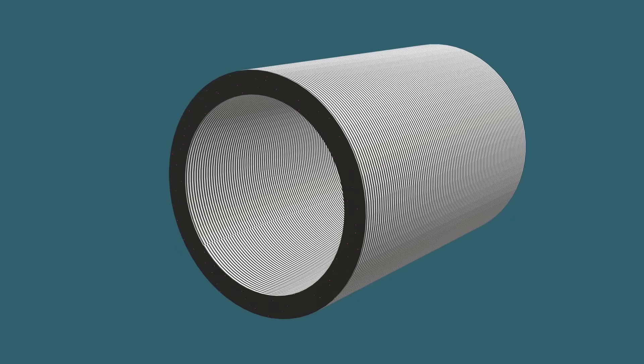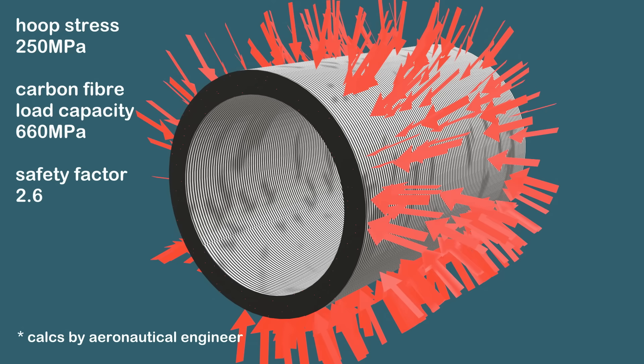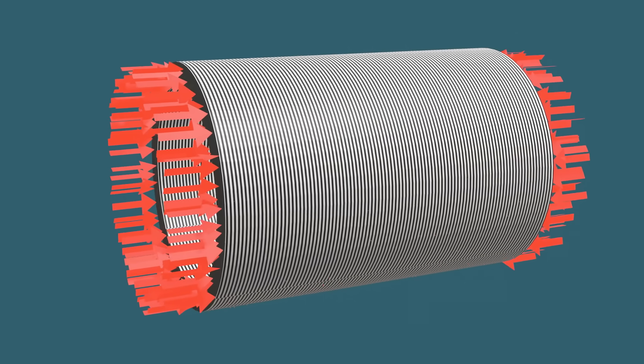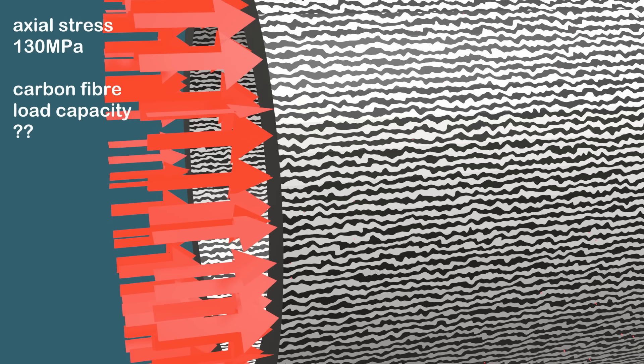Carbon fiber had the necessary technical strength for this application, so I suspect weaknesses in the layup process. Three quarters of the water pressure acts onto the face of the tube, and the hoop arrangement of fibres carries this massive compression force — they were more than capable of handling the load with a generous safety factor. A quarter of the force on the hull was from the pressure on the end domes squashing them together, and the axial fibres carried this load. This is likely where the problem lay. The geometry of the mandrel meant no tension was applied to these fibres, so kinks and wrinkles could not be pulled out. If the layup is bad, the load capacity is just a fraction of what it should be. I suspect the crooked longitudinal fibres progressively failed over the 13 or so deep dives.